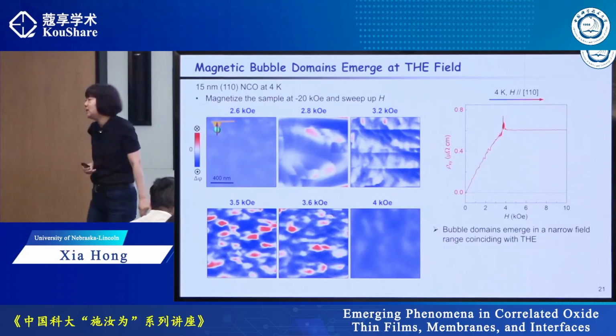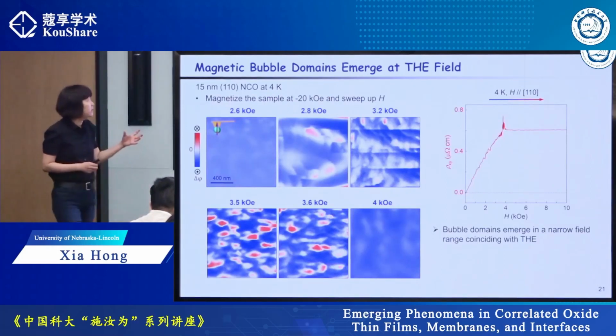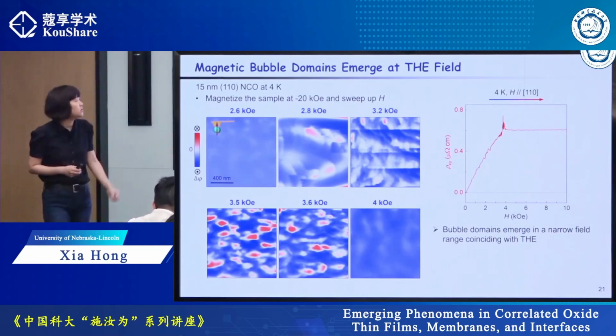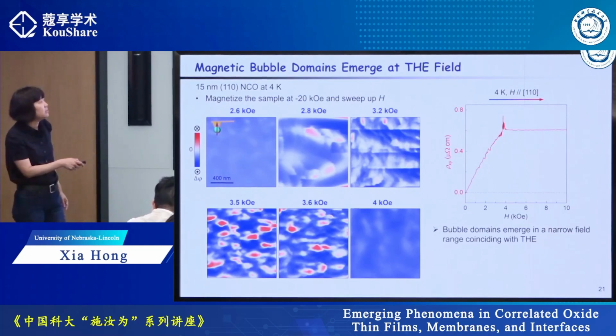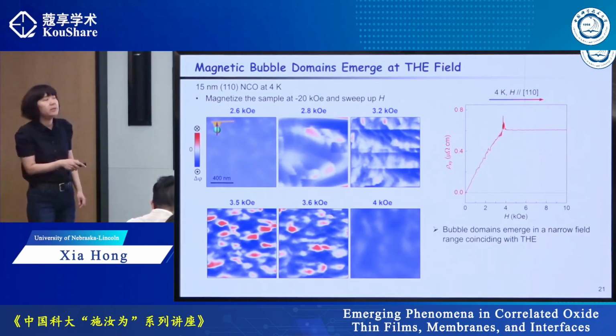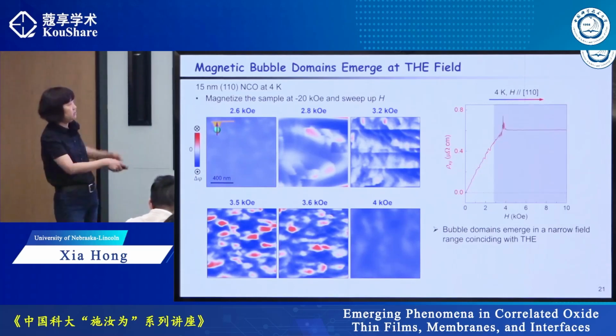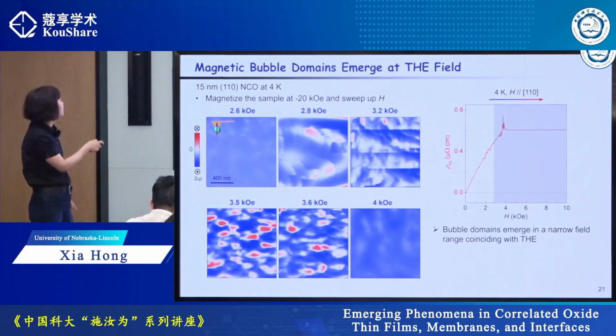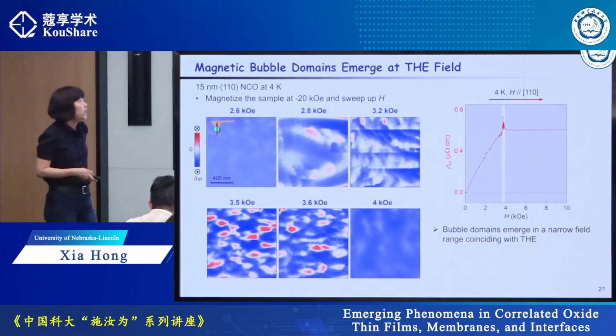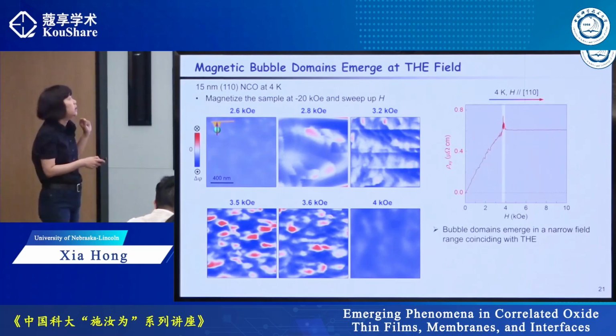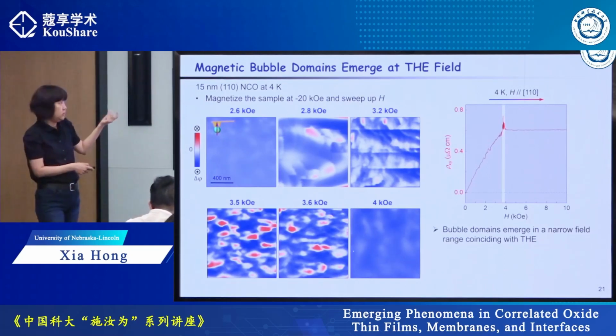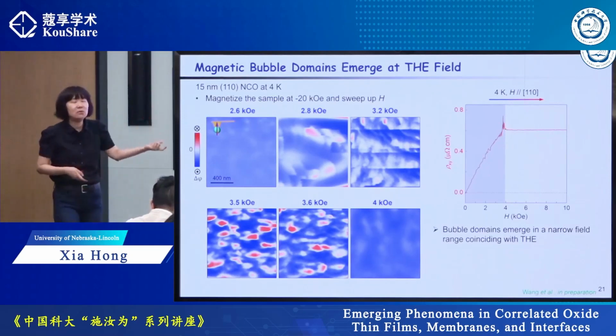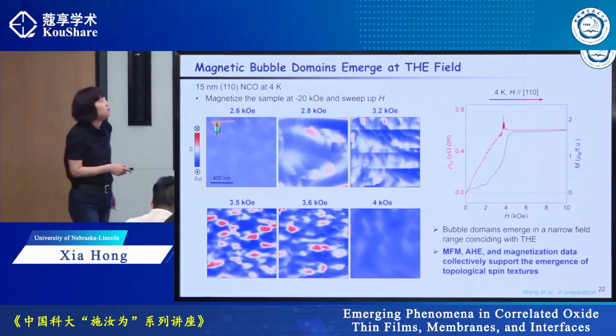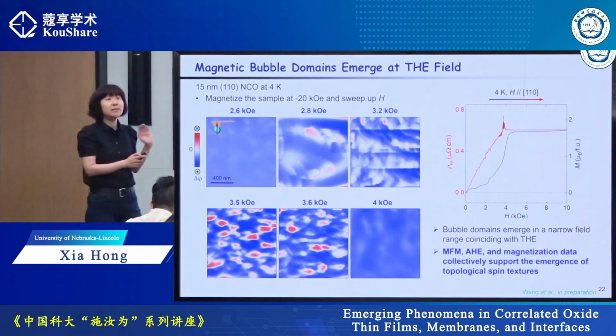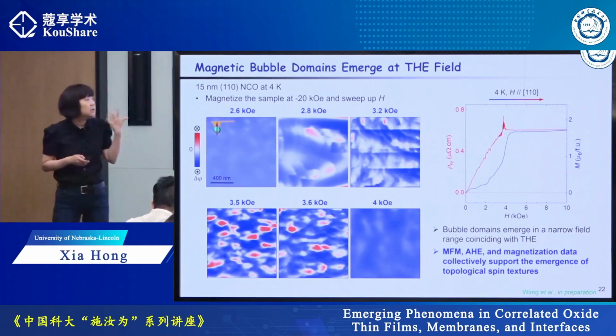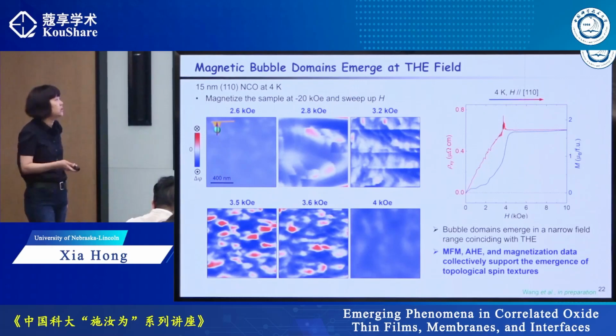To have a better idea whether we actually have magnetic spin textures, we did magnetic force microscopy studies. So this is the anomalous Hall effect. Let's compare it with the MFM imaging. If we are in the single phase region, you see only anomalous Hall effect, and basically you have a uniform single domain structure. When you are at the region where you see topological Hall effect, you are going to see magnetic bubbles. And going to high field, again, you have this single phase region, and your anomalous Hall effect appears only when the magnetization is about to saturate. So it does support that we have some topological spin texture that appears.